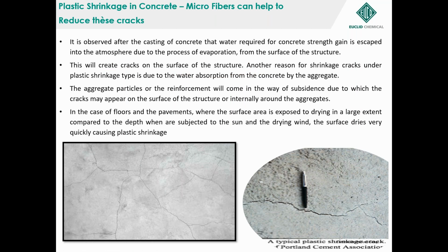So these are typical things which with microfibers we'll be able to eliminate. All of us know why plastic shrinkage happens. The water, when you put the concrete in, moves into the atmosphere, and voids are created. In those voids, you have a surface tension coming in when the water is sucked out from the concrete, and that creates the weak pore. And then you start seeing the cracks in this particular pattern.